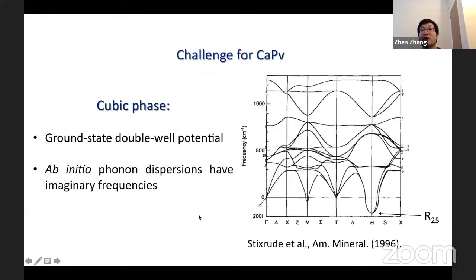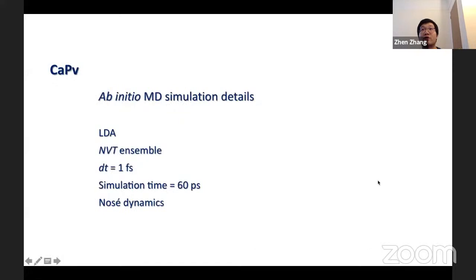Calculations of cubic calcium perovskite's thermal properties are also difficult due to the existence of imaginary phonon frequencies from perturbation theory. The imaginary harmonic phonon frequencies are associated with a ground state double well potential with respect to the finite displacement along the R25 mode eigenvector. For such a strongly anharmonic system with a ground state double well potential and imaginary phonon frequencies, the conventional perturbation treatments relying on finite displacement methods to calculate anharmonic phonon properties without renormalization of force constants fail.